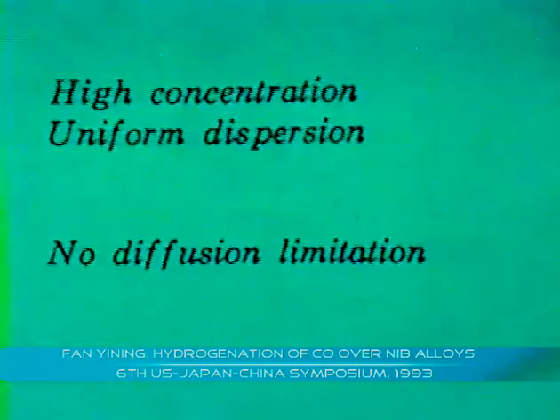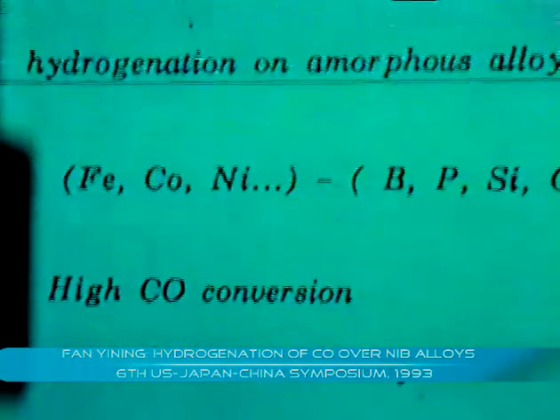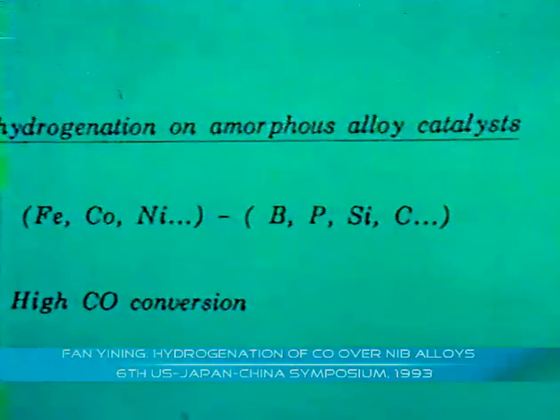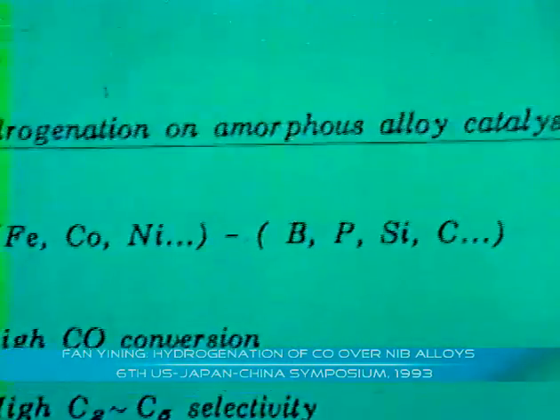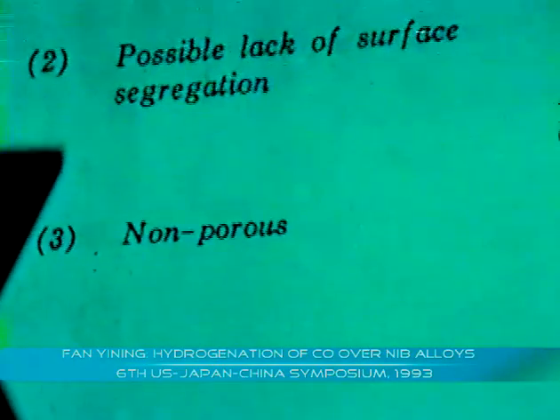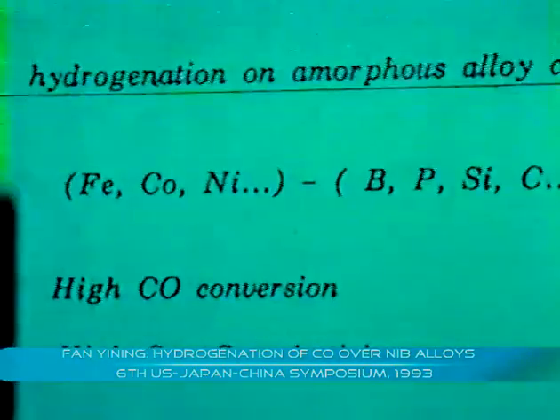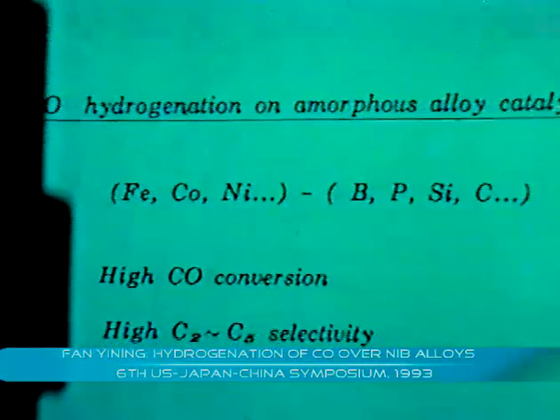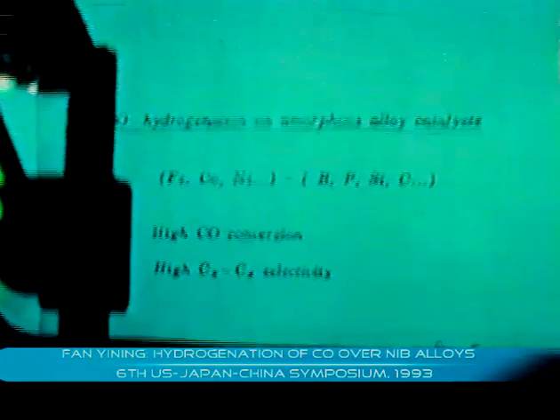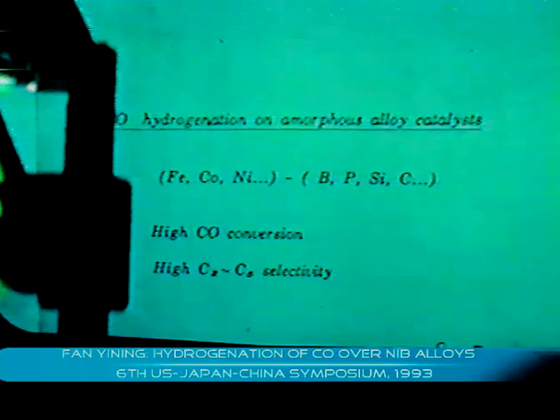The first is that amorphous alloys can be produced with a wide composition range, not available in crystalline form, which permits the continuous control of electronic properties of active sites. The second is that the atoms distribute homogeneously in the amorphous matrix, so the surface segregation of the alloy can be avoided. This makes a high concentration of active sites, and moreover, the active sites are dispersed in a uniform environment.